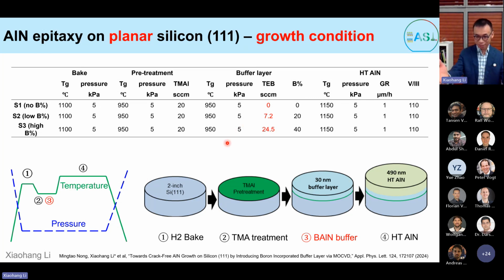So this is our epitaxial process, right? I think a lot of you are epitaxy experts here, so you are very familiar with this. We have three samples, okay? The first sample, sample one, has no boron. We grow a buffer layer of aluminum nitride, then we grow a thicker, about 500 nanometer layer of aluminum nitride at high temperature. For the second sample, we have a little bit of boron in terms of the boron flow rate. Here we use triethyl boron, TEB, which is commercially available as well. And then for the third sample, we have a lot of boron, right?